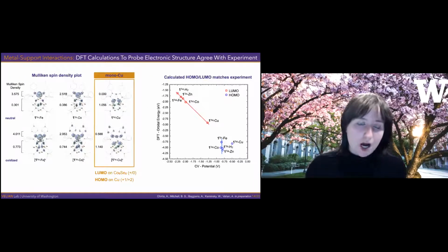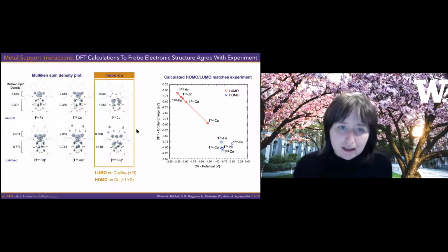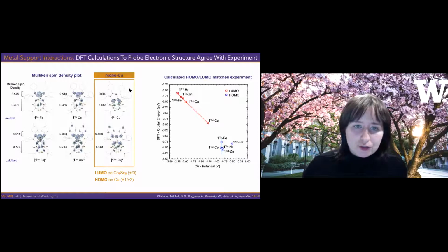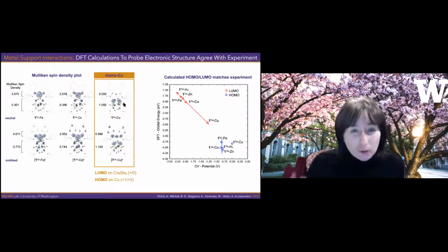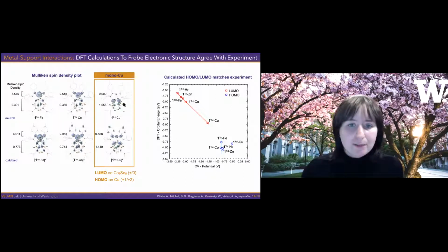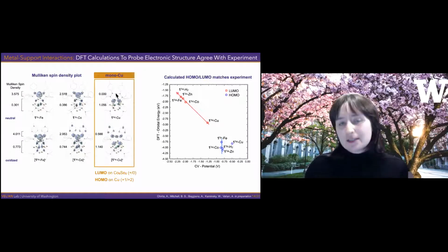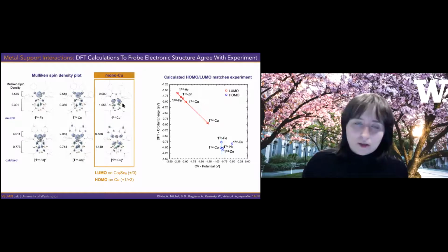But what's happening with the copper? So on the left, I'm showing you a calculated spin density plot. This just tells us where the unpaired electrons are. Well, they're estimated, they're calculated. And so I want to draw your attention to the copper system. So here's the copper, and in its neutral form, we start off with copper 2. So copper 2 should have an unpaired electron, but the spin density tells us that it does not. But now the cobalt core, which is diamagnetic, no unpaired electrons in its neutral state, has some spin density localized on it, and in a very anisotropic way, which is also kind of interesting.